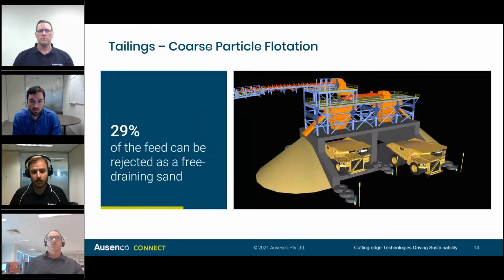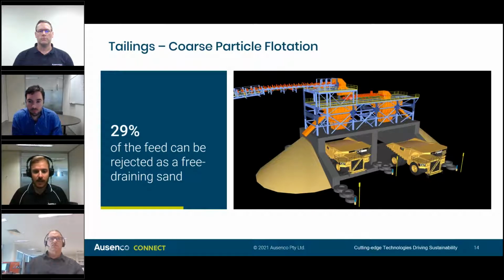And we're looking at this on a number of different sites. One of these sites at the moment, we're looking at the potential of actually rejecting the hydrofloat tailings, not combining them with the tails as happens at Cadia, but rejecting those tails through a sand plant that can remove the water from the free drain and produce a free draining sand that can then be trucked to a waste dump, or leached potentially, if there is some value there.